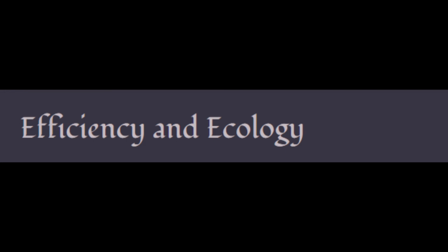Obviously, those figures vary wildly based on the quality and type of ore, the quality of our furnace, how well it keeps heat, for instance, and any number of other considerations. Healy, using some of Tylecote's figures, computes an estimate that Roman smelters, working continuously, 2 batches in 24 hours, might, in a day, produce 16 kilograms of iron from 100 kilograms of ore and 80 kilograms of charcoal.